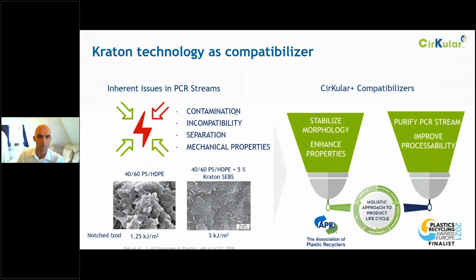You can never get completely pure polymer streams out of a recyclate unless, of course, you do chemical recycling, which is one step further and, in some cases, it's the only option. But of course, you want to stay as close as possible to the original polymer structure. So what we can do with our Circular Plus compatibilizers, and we developed them specifically for this market, is actually based on styrenic block polymer technology, but they are focused on this market. We can stabilize the morphology, we can enhance the properties. That's something we did already because SBCs are quite often used as an impact modifier in all kinds of plastics.